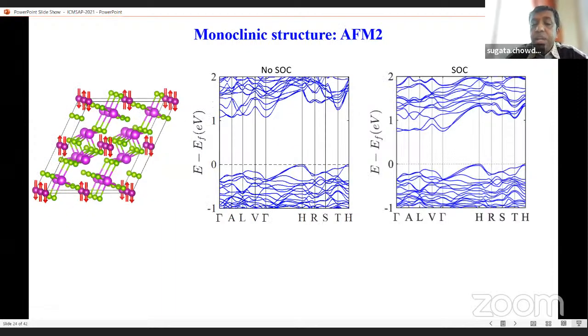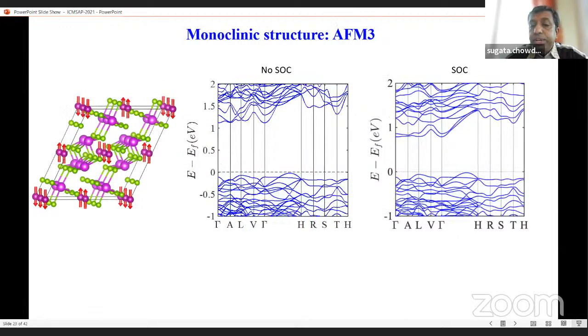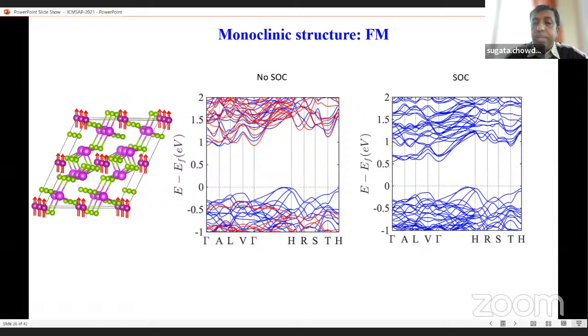Then he presented the antiferromagnetic case, and we found similar things: spin-orbit coupling plays a major role in the electronic property of this kind of material. He also did the ferromagnetic phase, and similarly spin-orbit coupling plays a major role in the electronic property of the material. So this is the detailed analysis of the differences between the monoclinic structure and the rhombohedral structure. This work is still going on, but here we concluded that the band gap for the monoclinic structure is about 0.5 eV, including SOC.